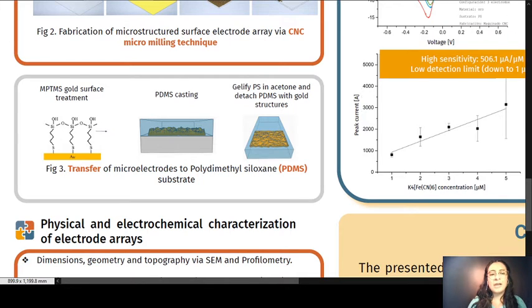a self-assembled layer of MPTMS is deposited on top of the gold layer to promote good adhesion between the metal and the PDMS. Next, PDMS gel is cast on top of the device and cured at 60 degrees Celsius. Finally, the composite is submerged into an acetone bath to induce gelification of the polystyrene and be able to remove it from the surface.